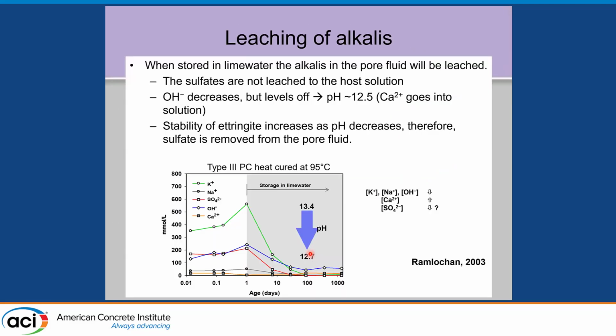And again, this just shows the leaching. At 1 day you've got the sulfate in red here, and the alkalis, say potassium, in green. And at 1 day you put it in lime water after the heat curing, and then they start to leach out. So they come down, the pH drops, not to really low numbers, still above the corrosion threshold. So they're going from 13.4 to 12.7, which is quite a bit.